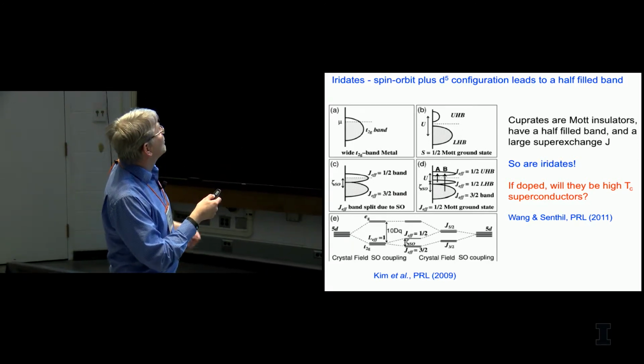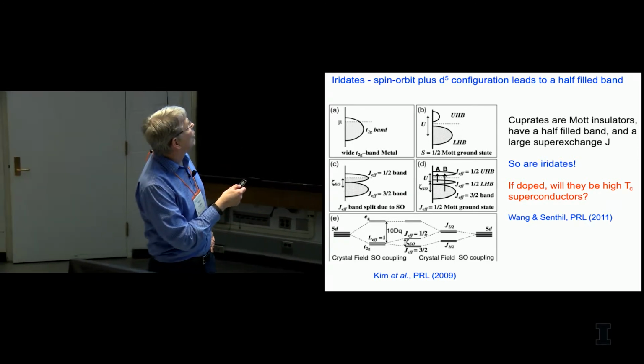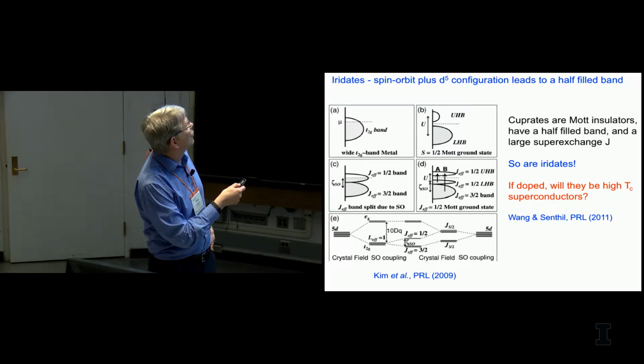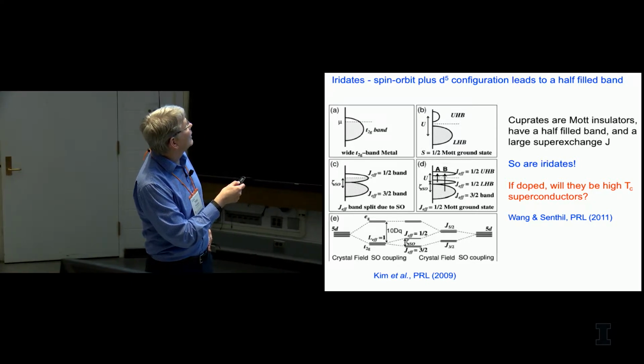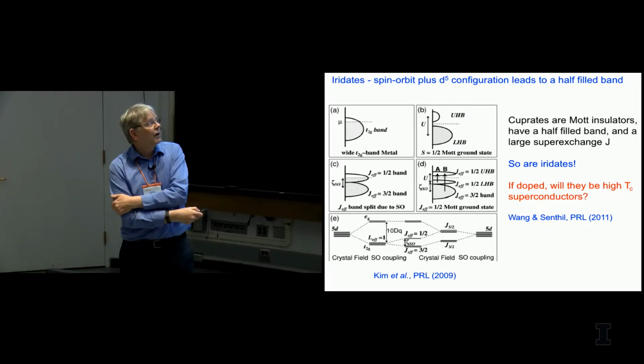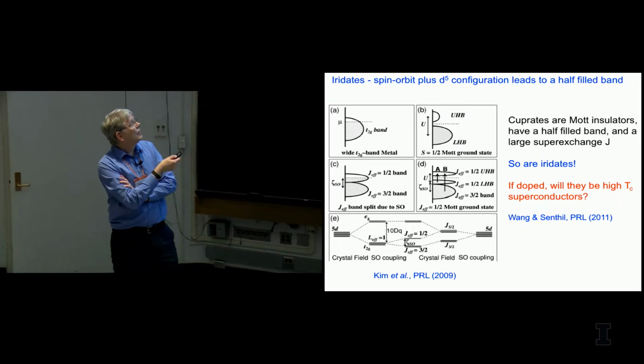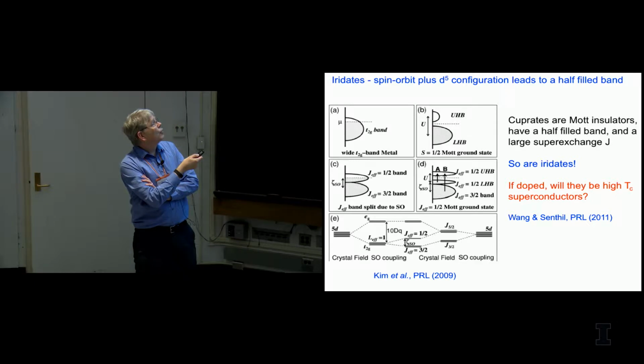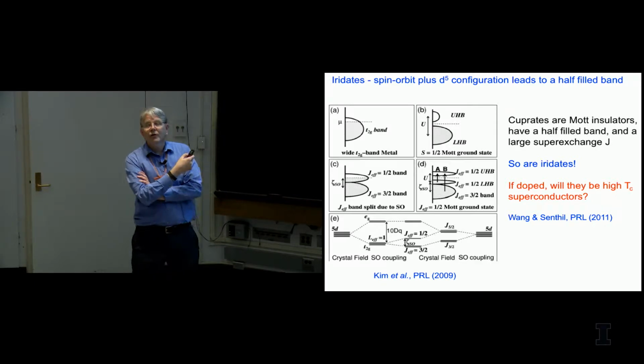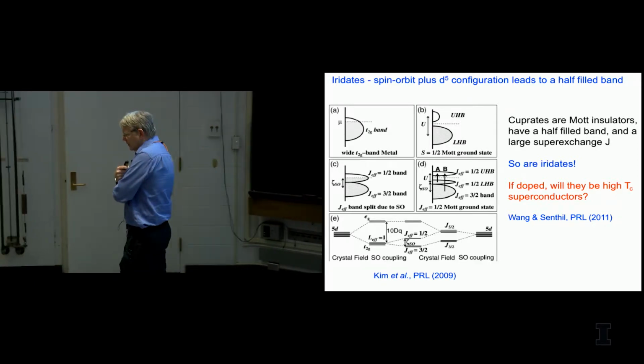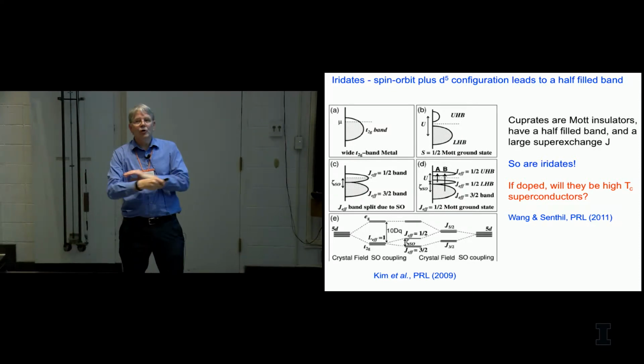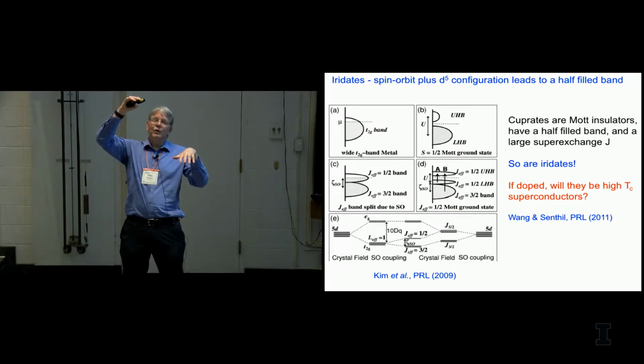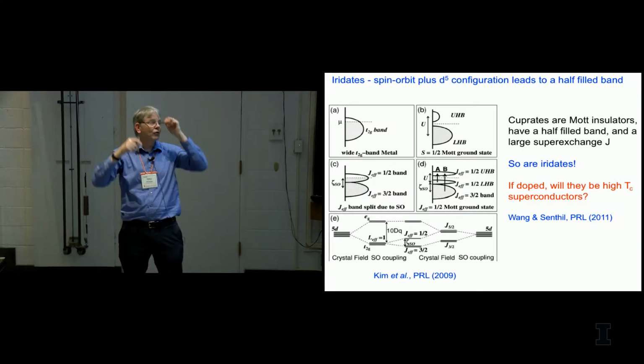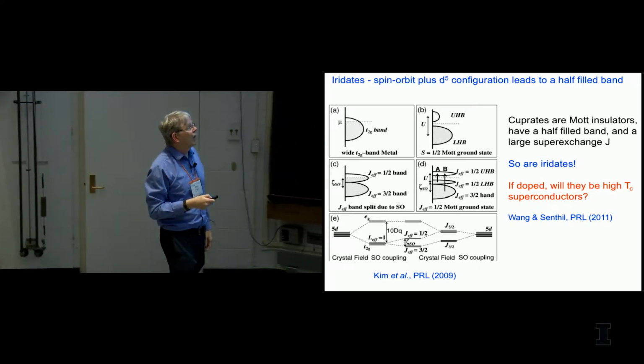And iridates became a big subject about 10 years ago because it turns out that because of spin-orbit coupling, the t2g bands in this material become a quartet and a doublet, and you have a half-filled doublet in the iridium case. So you have a half-filled band just like you have in cuprates, and the idea was whether this would be a cuprate analog. The issue in the iridium case is that the iridium-oxygen p bands and iridium d bands are not close together like they are in the cuprate case.